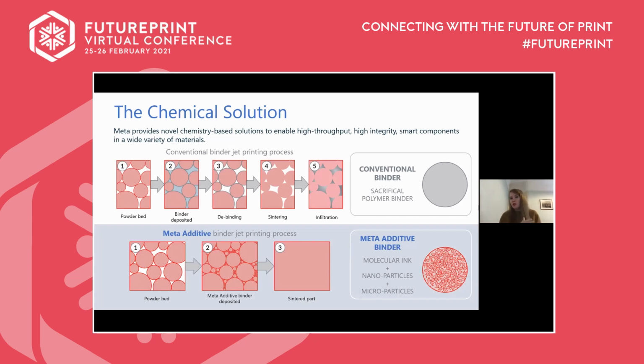So you have your usual powder that you layer upon, you use an inkjet head, and we'll come on to those shortly, but you use those inkjet heads to print what we call a functional binder. And we are binding and simultaneously infiltrating our powder bed. So there's no debind step because we're not using polymers, we're not using a sacrificial binder, we're using a functional binder.